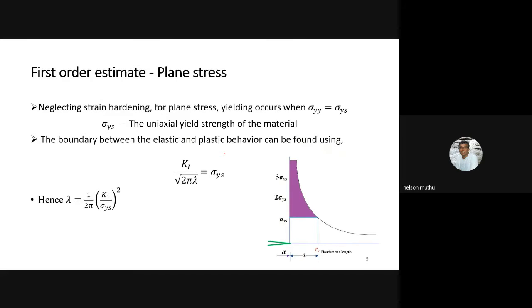So as a first order estimate, as I said to you before, once you neglect the strain hardening and for plane stress, the yielding will occur when sigma yy will be equal to sigma ys. Again, this is based on the Tresca's criterion, and sigma ys is nothing but the uniaxial yield strength of the material. So you can use this relation straight away: K1 by square root of 2 pi lambda will be equal to sigma ys. So from there you can estimate what is the value of lambda.